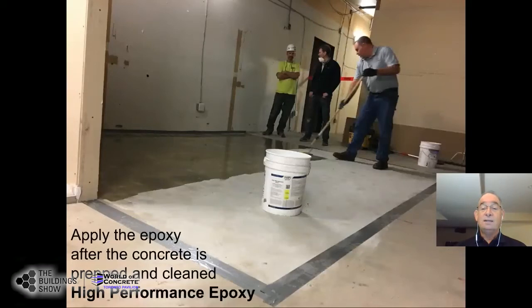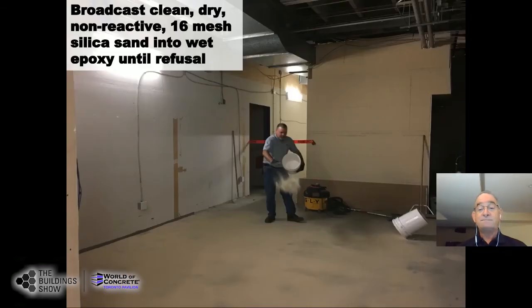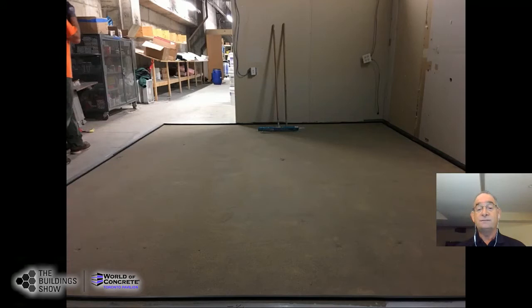So here we're applying the epoxy. The epoxy is applied first to the well-prepared surface. Then a broadcast of dry silica sand is applied to the surface to refusal. So we don't want to see any wet spots on the floor itself. This is what it looks like after the aggregate has been applied. So now we've got a saturated epoxy surface with this sand.